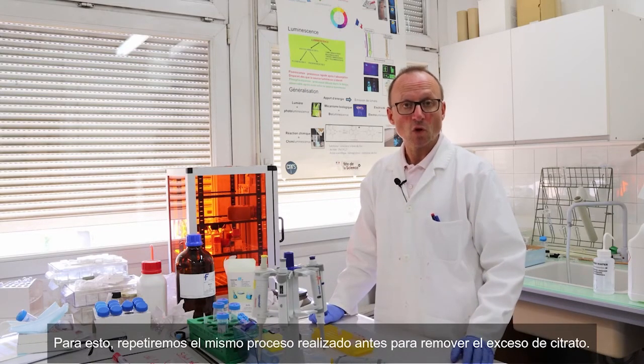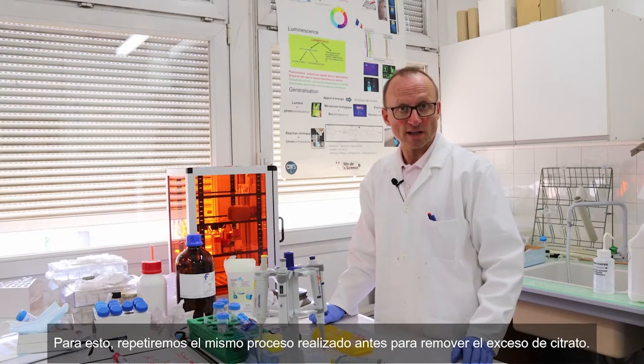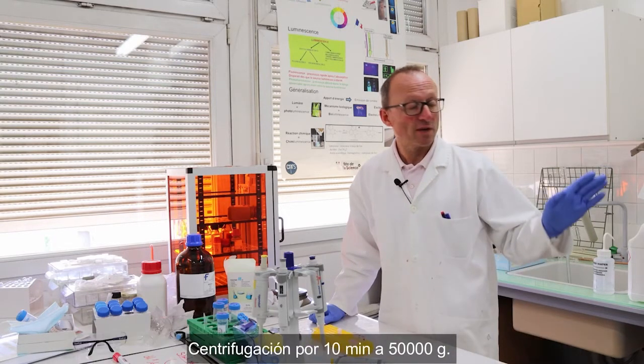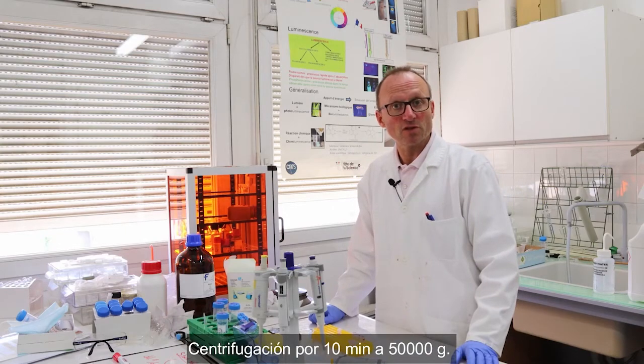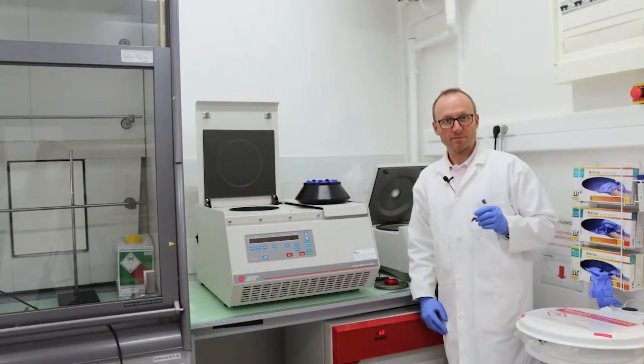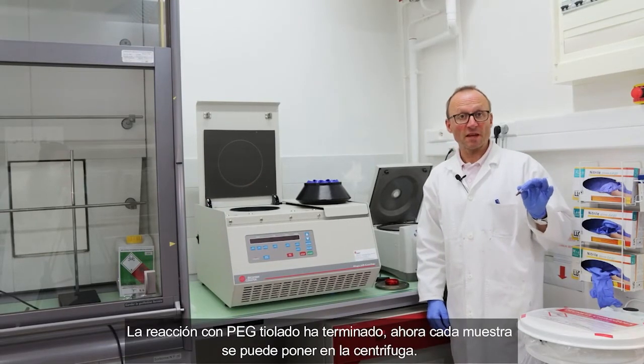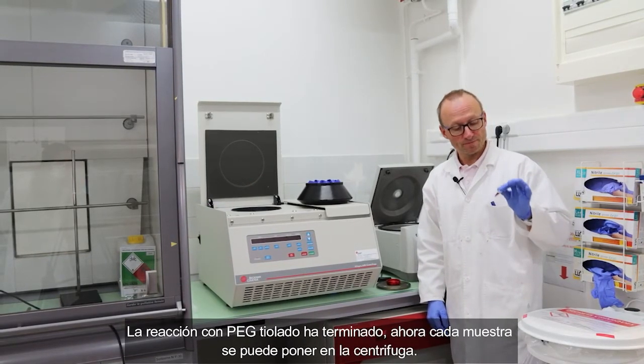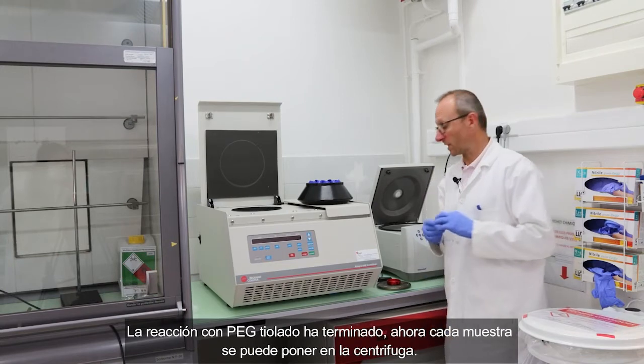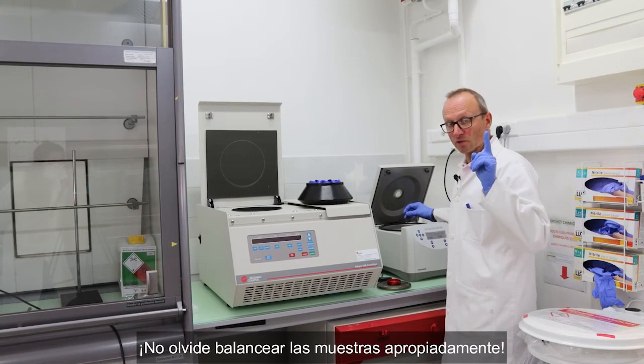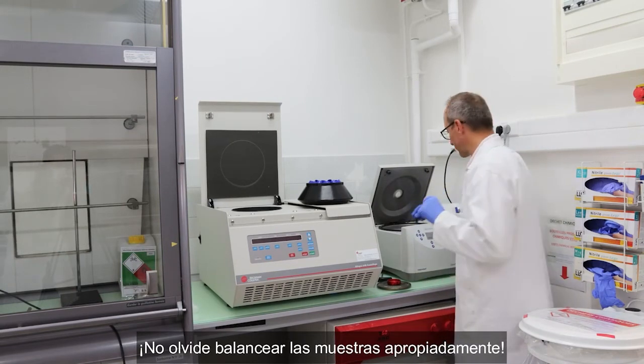To do that, we'll do it the same way as we did before to remove the excess of citrates, using a centrifugation step for 10 minutes at 50,000 Gs. So the reaction with the PEG thiol is done now. So each sample can be moved into the centrifuge. Don't forget to properly balance all your samples.